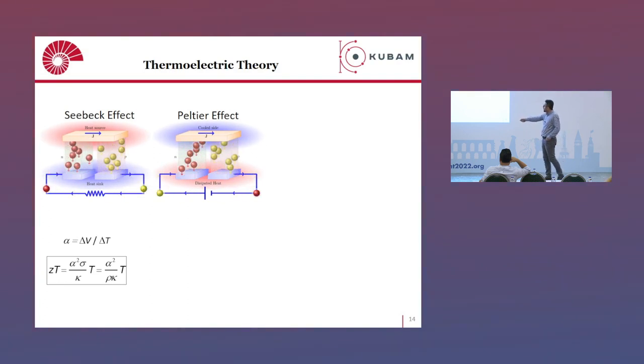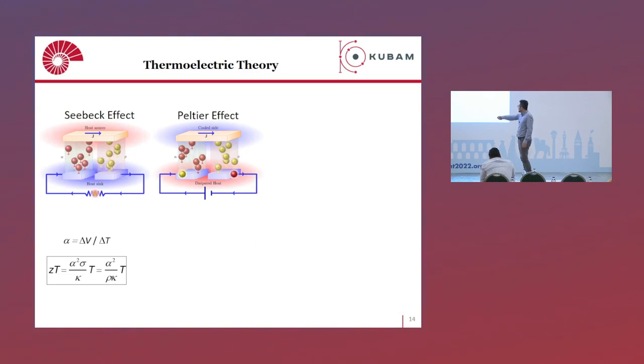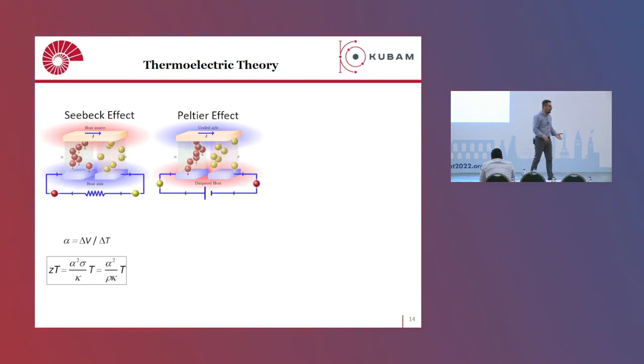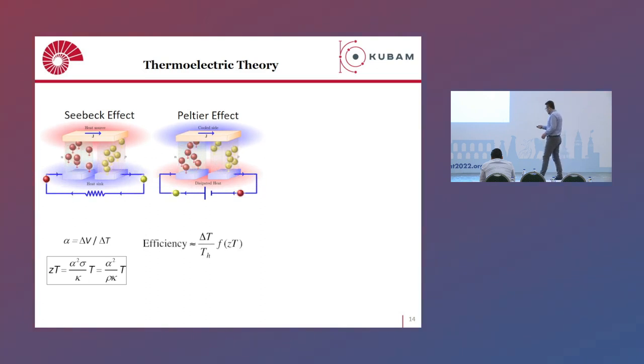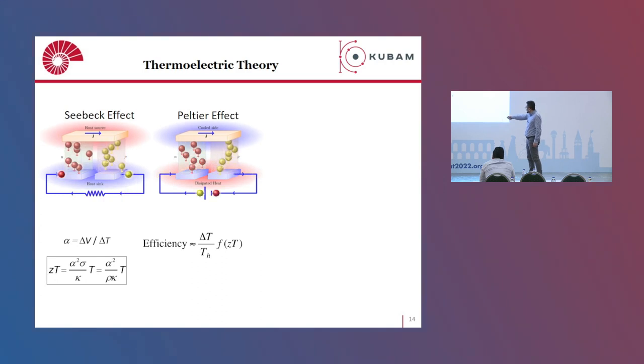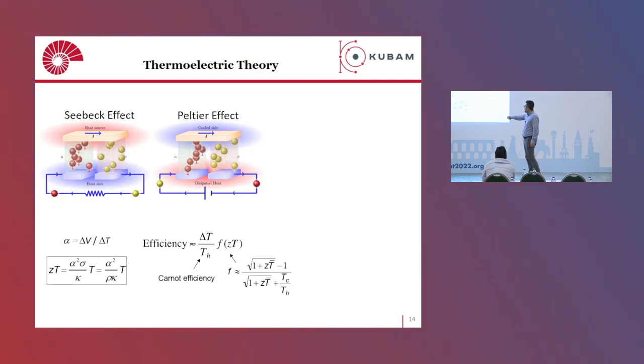So in the materials part, we have ZT, the dimensionless thermoelectric figure of merit, related to the Seebeck coefficient squared times the electrical conductivity, divided by the thermal conductivity, times the temperature. For high thermoelectric efficiency, we try to get good electronic properties but at the same time lower the thermal conductivity, which is quite demanding and hard. Device efficiency is related to the Carnot efficiency times a function of the material ZT. Rather than having a high ZT at one particular temperature, we target a high ZT over a large temperature window so that we have a high average ZT.